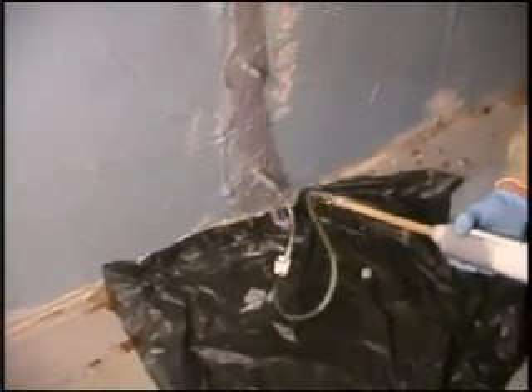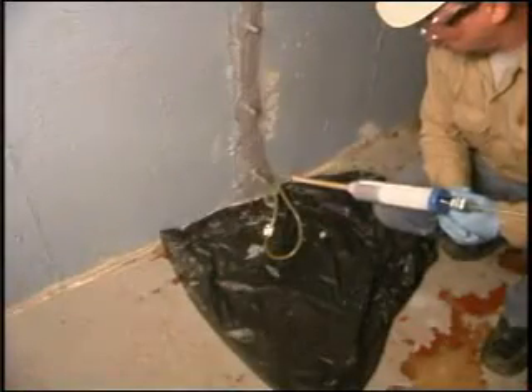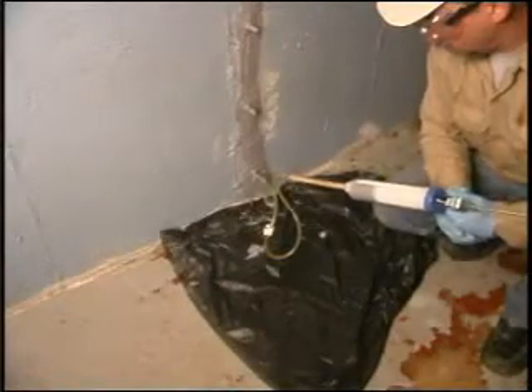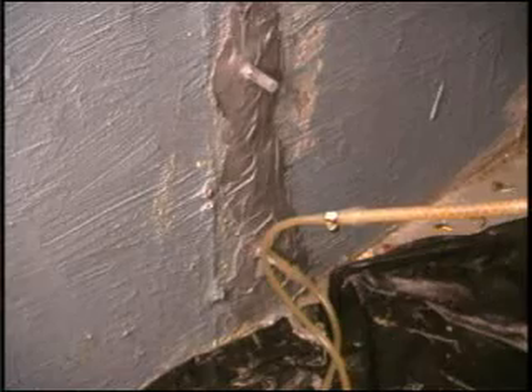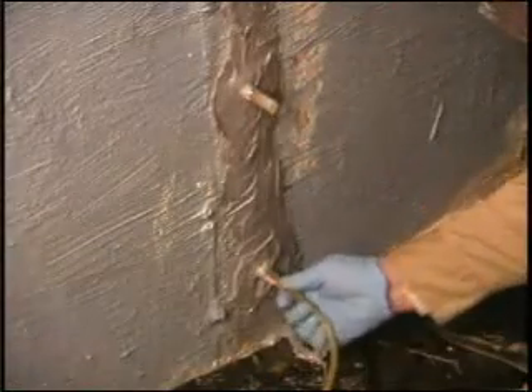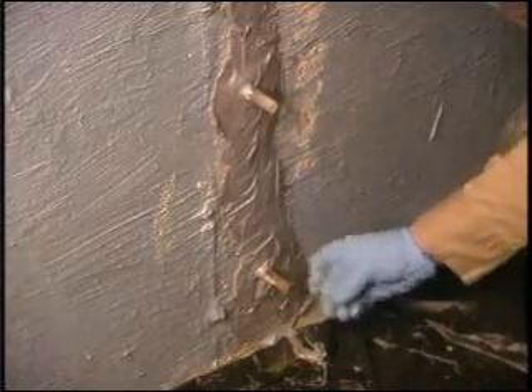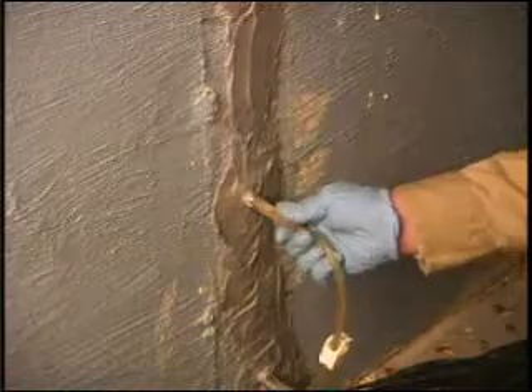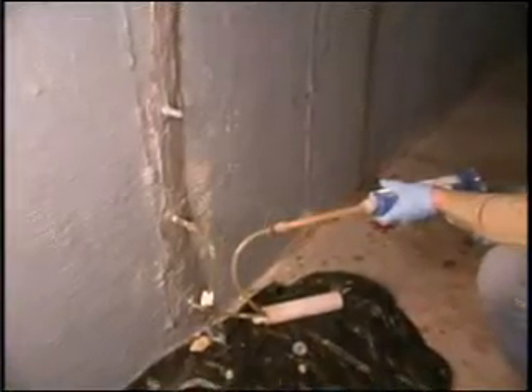Begin injecting slowly with low pressure, allowing the resin time to flow into and fill all small fissures until the resin begins to flow from the port above it. Use the white plastic pinch valve on the hose assembly to turn off resin flow and remove the hose. Plug the first port with the cap provided and move up to the next port. Repeat this procedure until the entire crack has been injected with resin.